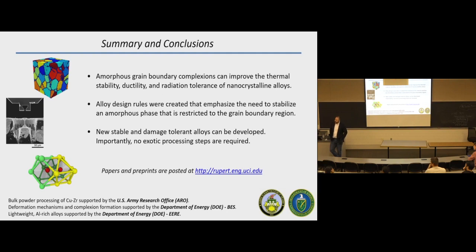What we're actually kind of excited about, and probably more on the radiation side, is that you should be able to, just like you can with glasses, rejuvenate that structure. So if you absorb a bunch of dislocations and change the structure over time, you could take it out of service, heat it back up to near the melting point, quench it down, and it would recover that structure. So I think you could do that. Now we're making thought experiments. I haven't tested that, but I think it should be possible.